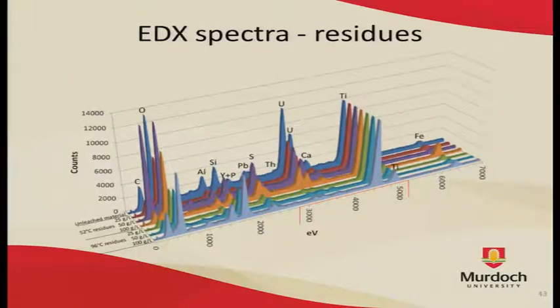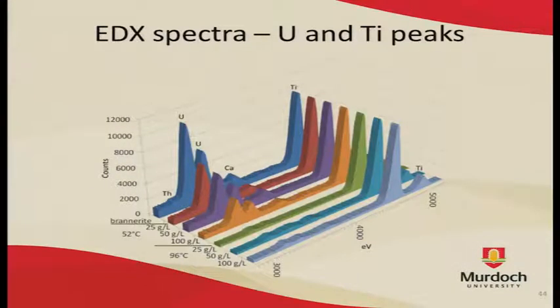Here are just selected EDX spectra of some of the residues. They're all normalised to that titanium peak there. We've got the initial material at the back, the 52 degree residues in the middle, and 96 degree residues towards the front. Now, the uranium peaks are much lower in the 52 degree leach residues and near absent from the 96 degree residues, which is a bit easier to see when we just look at the relevant area. The uranium peaks are much lower after leaching at moderate temperature, and are near completely absent from the high temperature residues. So at high temperatures, it's pretty much just complete conversion into titanium dioxide, with most of the uranium entering solution.